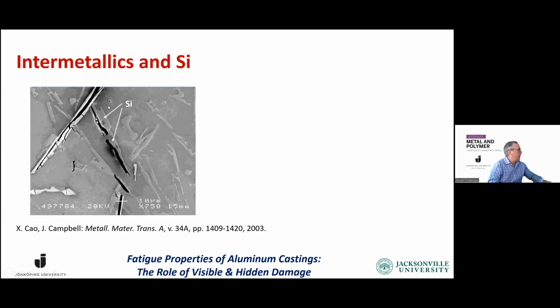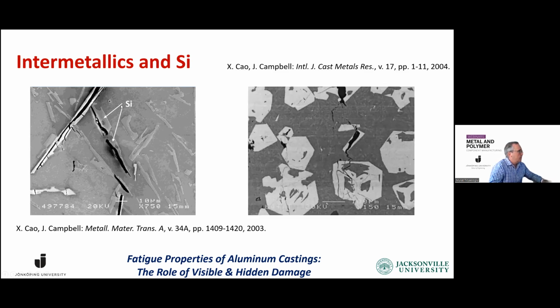Here on the upper left side, you see a completely cracked beta platelet, and right next to it are cracked silicon particles. And we're going to see that there are also sludge particles that are cracked. The cracks are not only in the particles, but also in the aluminum matrix. What's fascinating about these cracks is that there's no tensile stress. Nothing has been applied to these. These were allowed to sediment to the bottom during the casting process, and they just opened up.